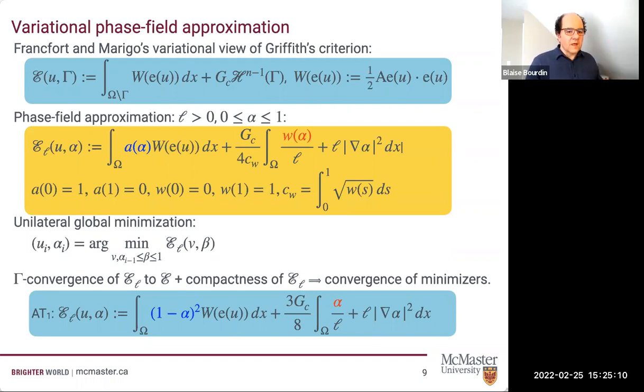And so what we did in the mid-90s was to borrow this idea coming from the image processing community, and to build a phase field approximation of the Francfort and Marigo energy. That is, to introduce an order parameter alpha that is a smooth function taking values between 0 and 1, a regularization parameter, and two interpolation functions: a function A that is monotonically decreasing from 1 to 0, and W that is monotonically increasing from 0 to 1, both of them smooth, and postulating or constructing this energy.